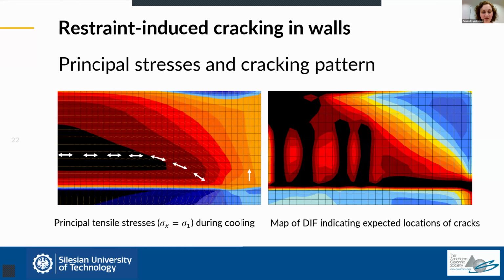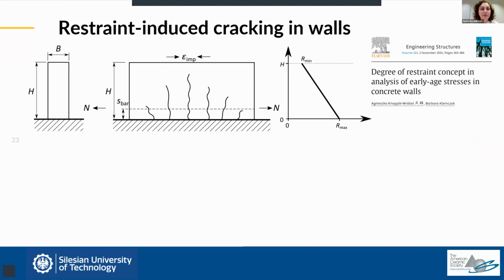So how we also understand the principal tensile stresses is that the cracks will form in the direction perpendicular to these tensile stresses, and they will open in the direction which complies with the trajectory of the tensile stresses. So by this simple stress analysis, we have explained why we observe such shapes of cracks. And now how we apply it in the modeling. So we are coming back to this simple tie model.